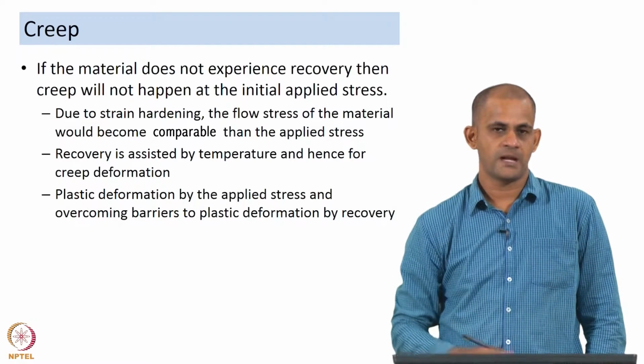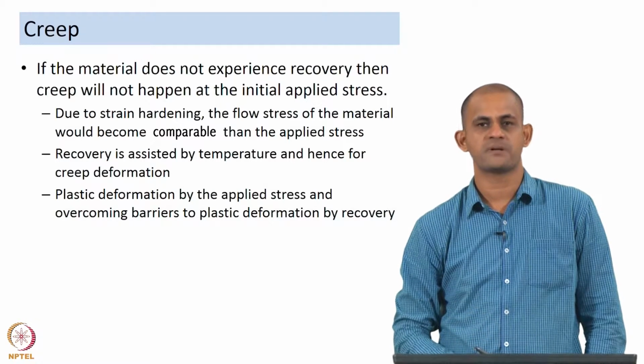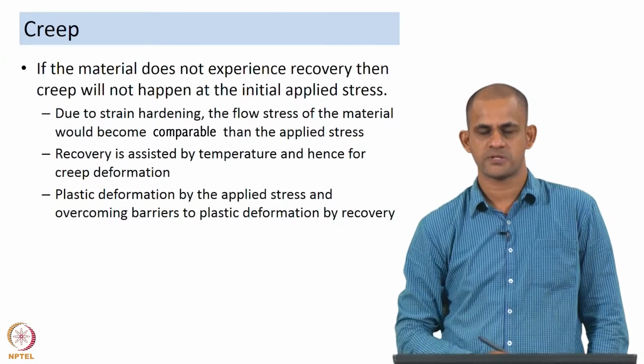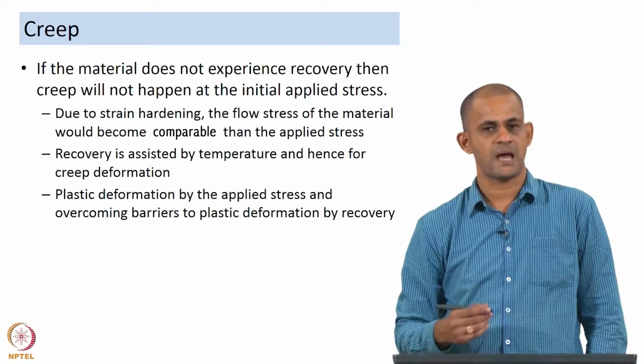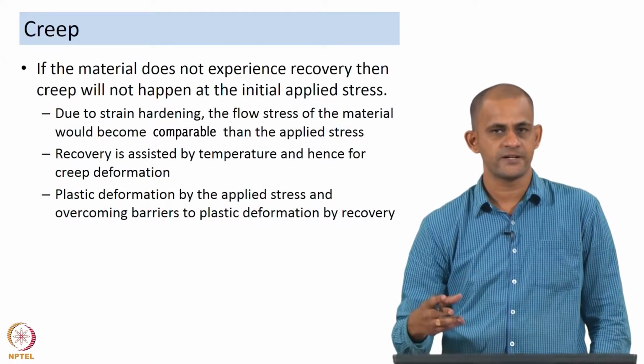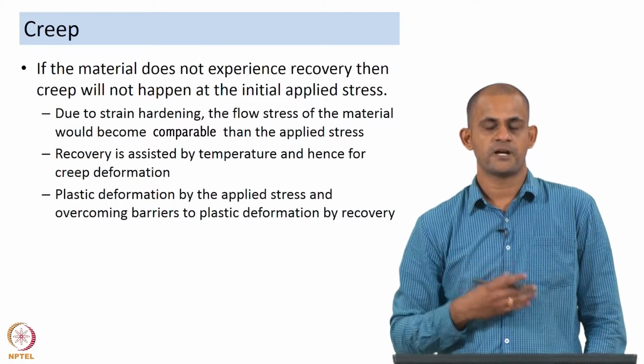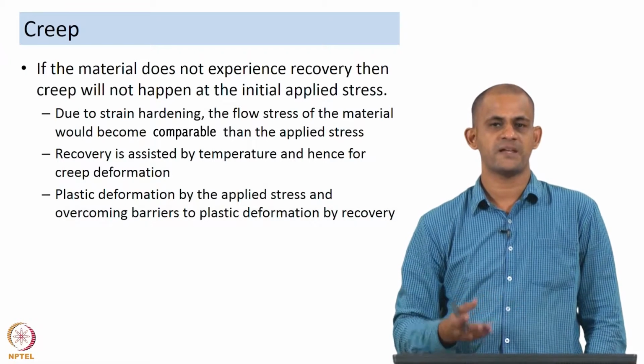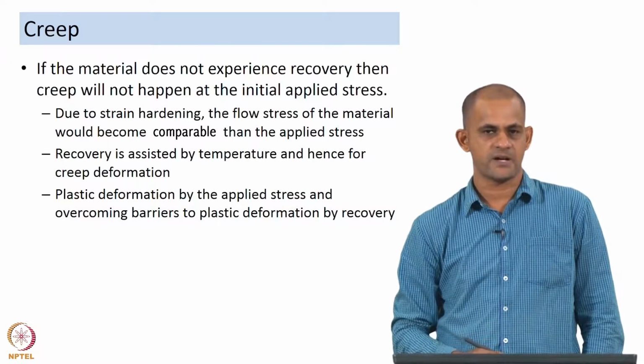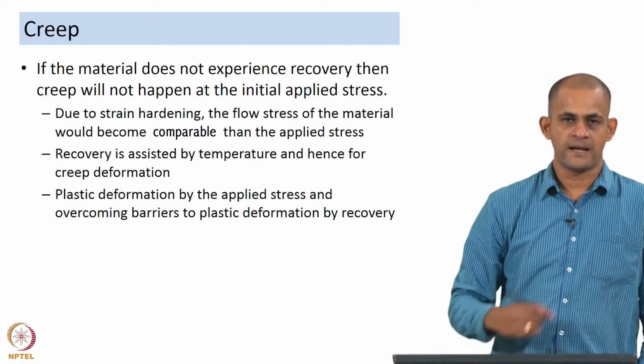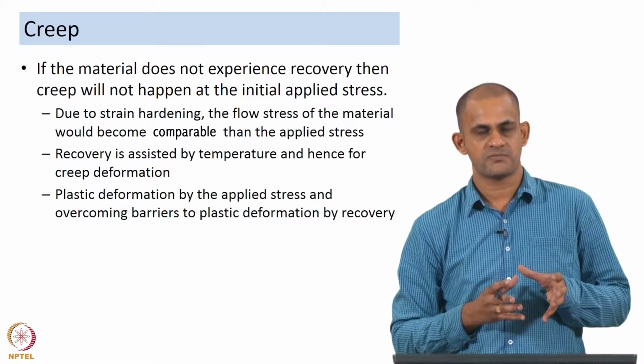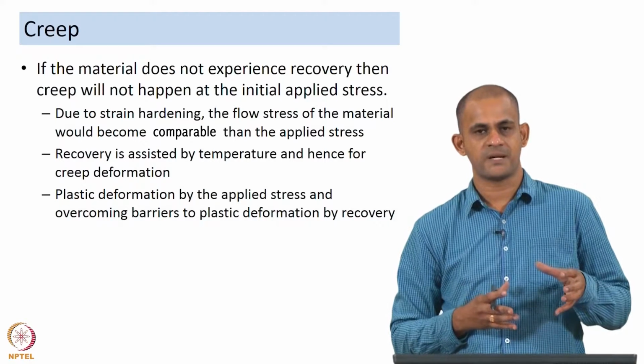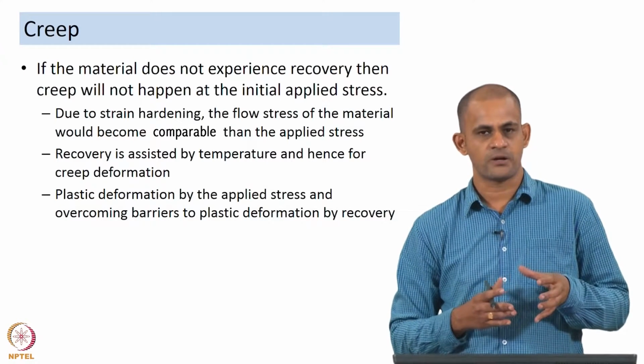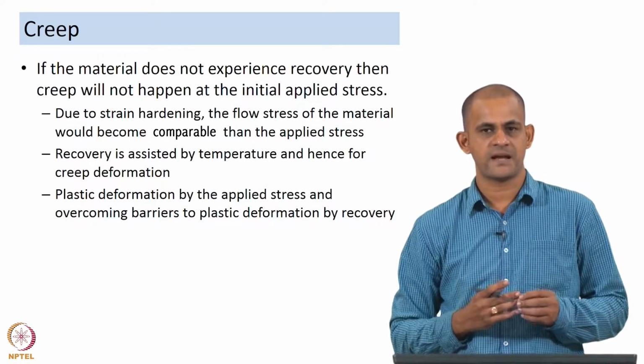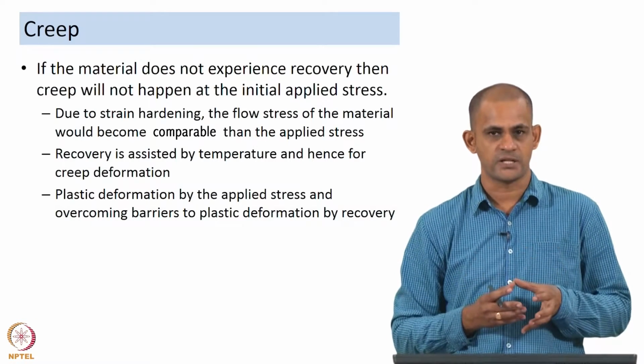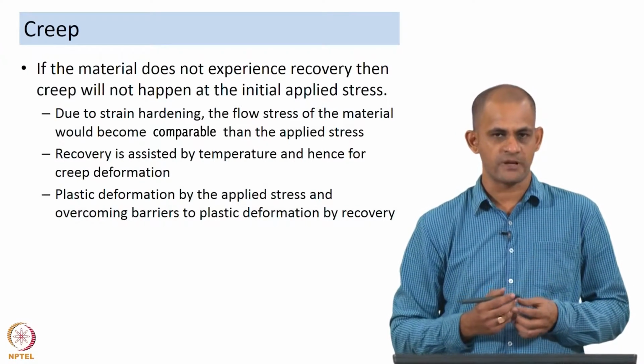So, up to the last point, we were talking about subgrain formation in titanium alloys during the process of creep. The subgrain formation happens because the dislocations that are getting hindered during their motion try to overcome those barriers by recovery. The recovery process requires high temperature. And that is how you have the subgrains, where the boundaries of the subgrains consist of arrays of dislocations, and the subgrain region is more or less strain free.